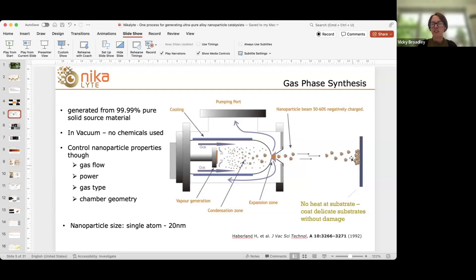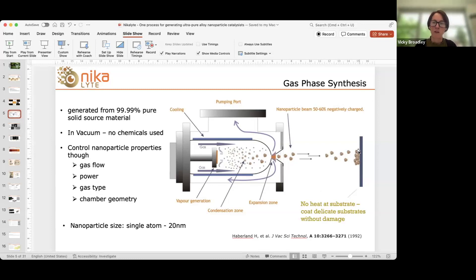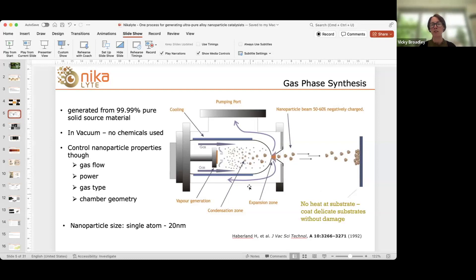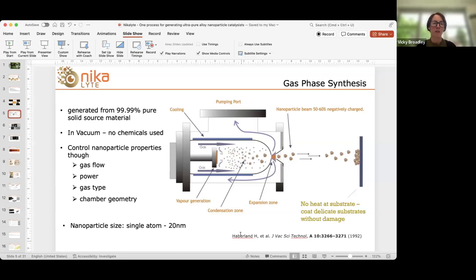By changing all these parameters we can control the properties of the nanoparticles generated. The nanoparticles are drawn through the exit nozzle into a separate vacuum chamber — the substrate or deposition chamber. As they exit, their properties are frozen; they've cooled and formed their final structure. The nanoparticles land onto the surface where we form a coating — either a dispersed coating of individual nanoparticles or a three-dimensional nano-coating with a built-up layer of highly porous material. There are many applications for nanoparticles generated by this technique.